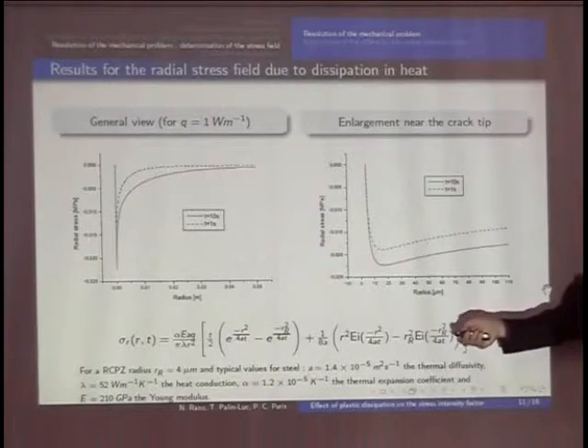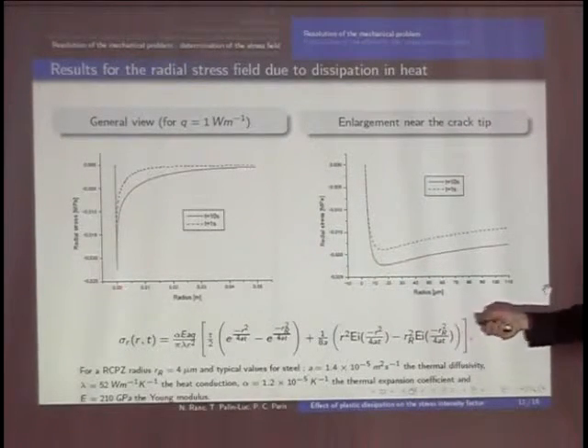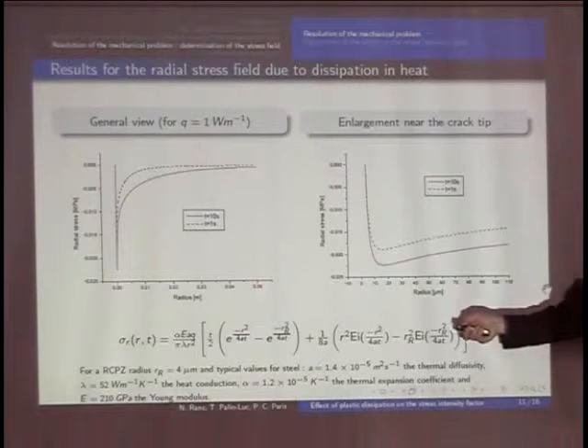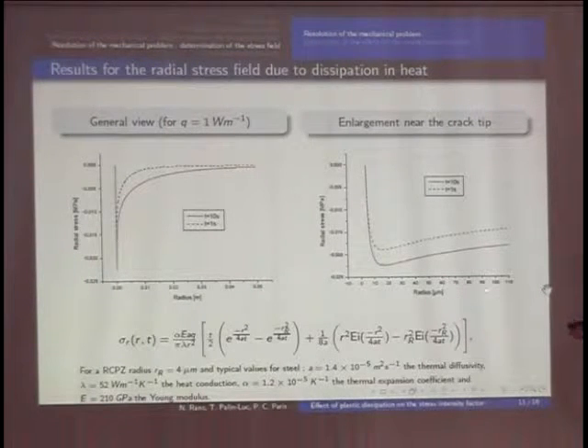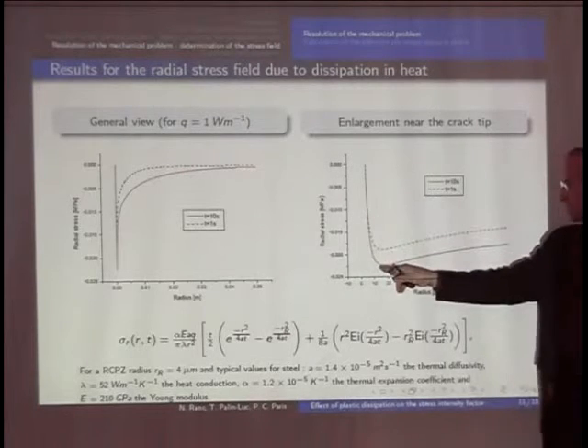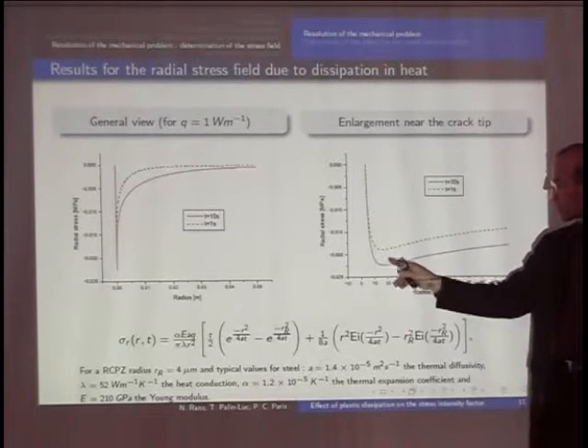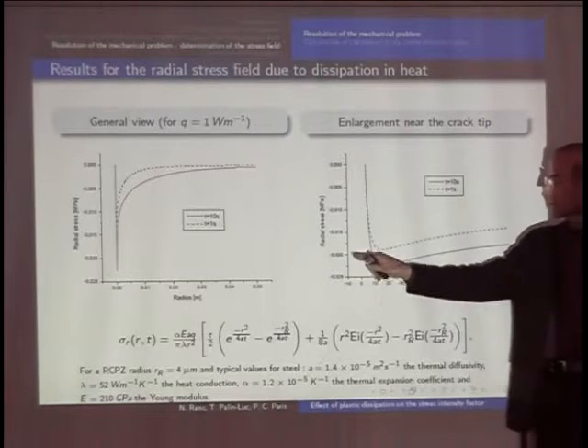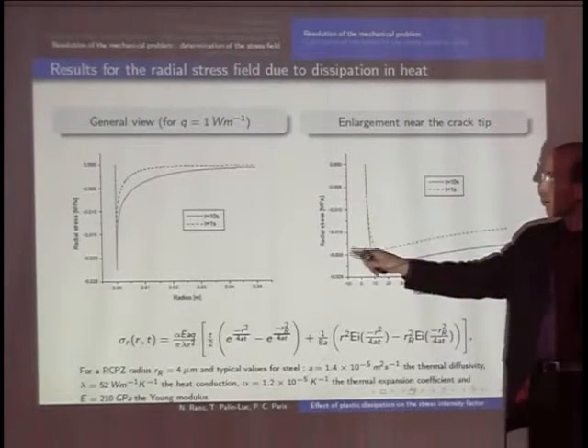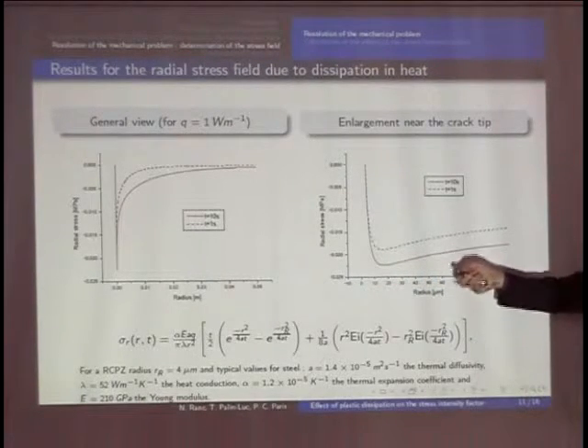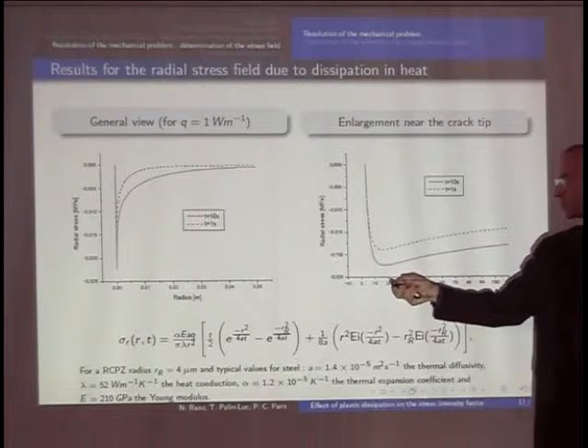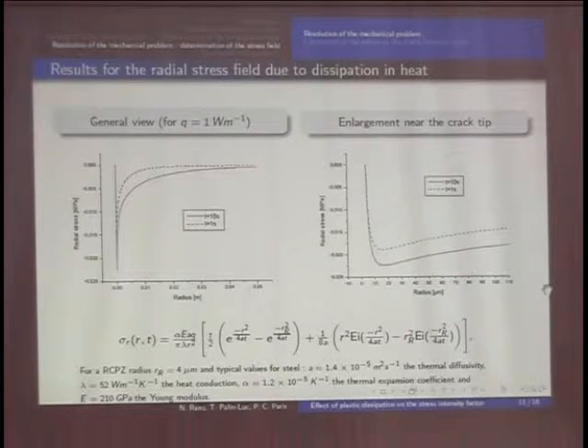If we zoom on this peak, the scale here is meter and now we are in micrometer. You can see that there is a peak which is moving a little bit with time. The values are very small, always because we have a unit heat source. Here we have minus 0.02 megapascal.